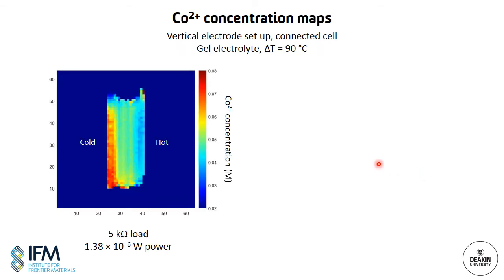Strangely, in the gel sample, we actually saw the reverse of what we expected, with cobalt 2+ concentration very high on the cold electrode side. And this may be explained by an initial concentration gradient caused by thermophoresis. Thermophoresis results in heavier molecular species moving along a temperature gradient towards the cold direction.